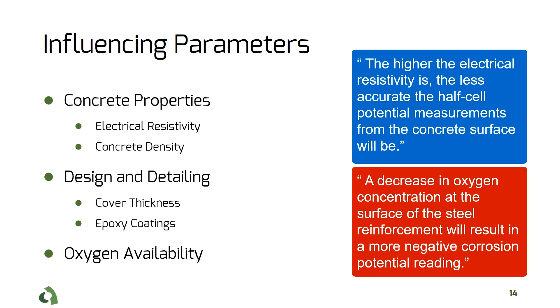There are some complications along the way when performing a half-cell measurement. High electrical resistivity of concrete cover, decrease in the moisture content of concrete as well as an increase in the thickness of the cover, make half-cell readings less accurate.